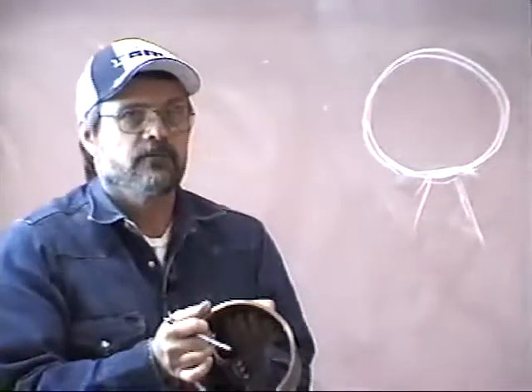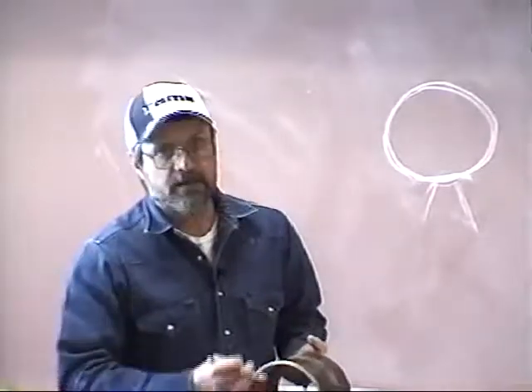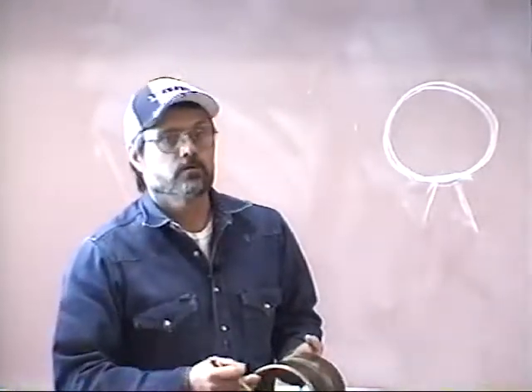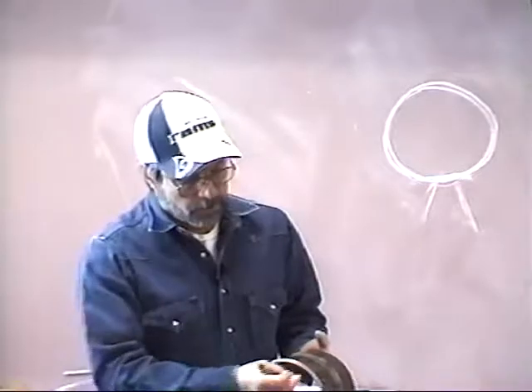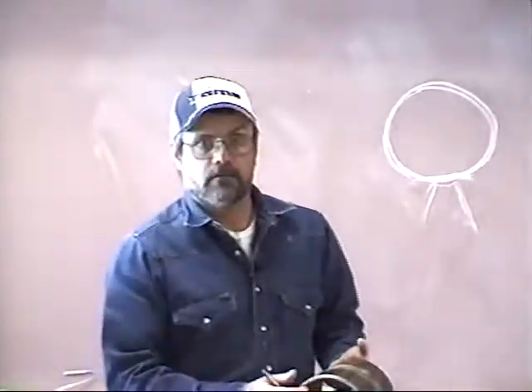Usually if you have lack of penetration, if that keyhole is too small, it's because you're either running too cold or you've got too thick of a land on it. That's why I say preparation of the joint is essential. Remember, we want that land to be 3/32 of an inch when we're welding in the vertical up position, and we want it to be not more than a 1/16 of an inch when we're welding vertically down.